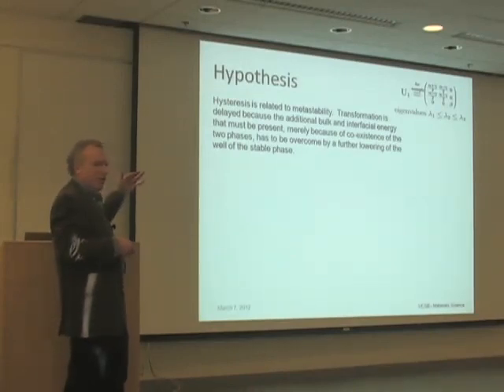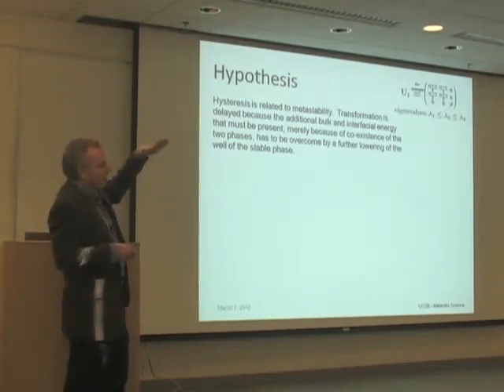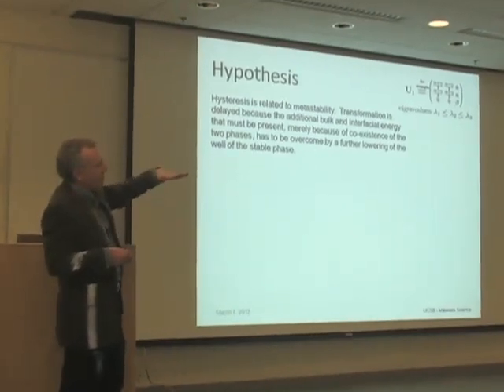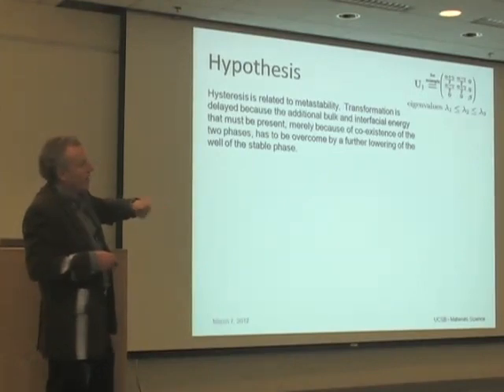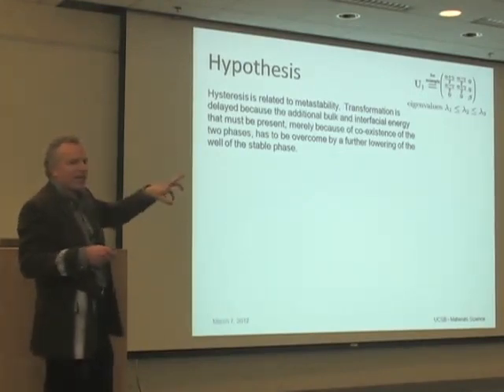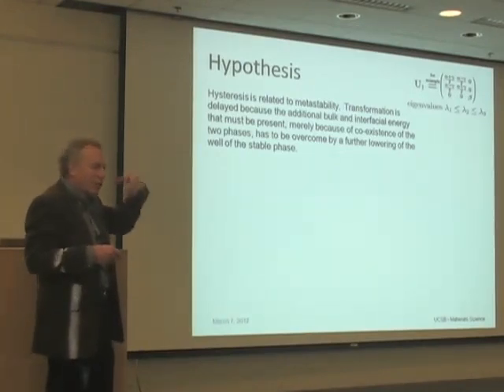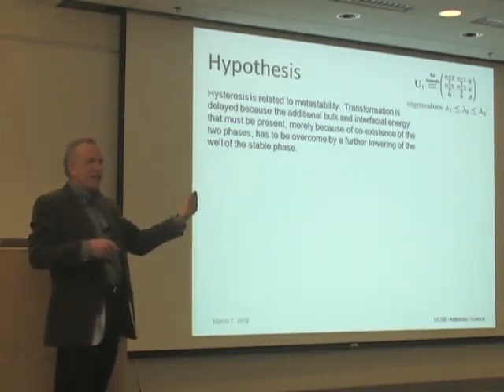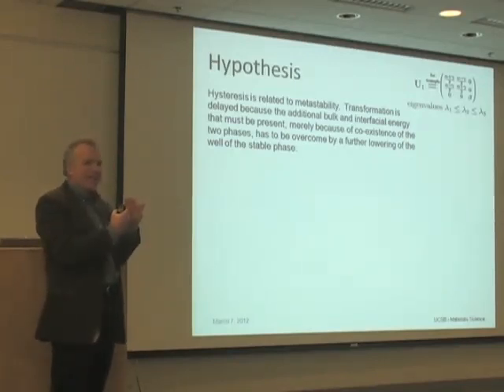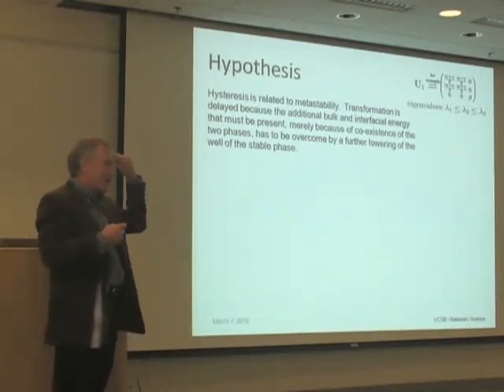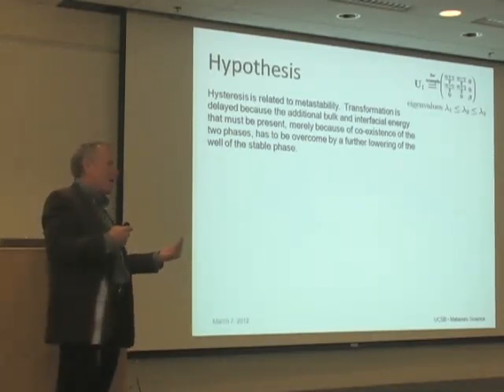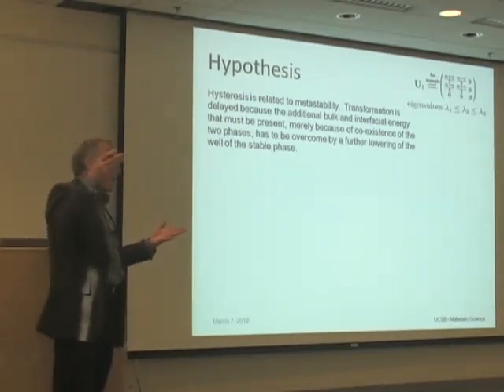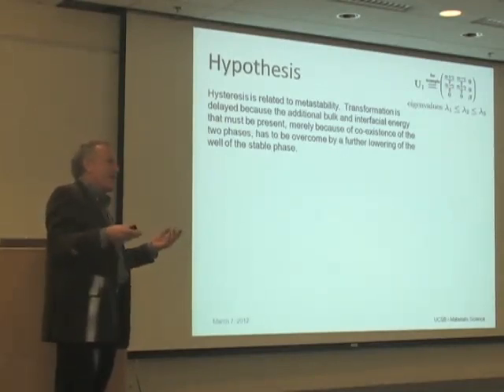And the idea is the following. You're cooling the material through the phase transformation. You have no martensite there. Martensite starts to form. But as soon as it forms, there's this extra energy just because austenite is against martensite. And you have to pay for this energy. You pay for it by having to lower the temperature more, to make the free energy of the new phase lower, to have a free energy decreasing path through the phase transformation.